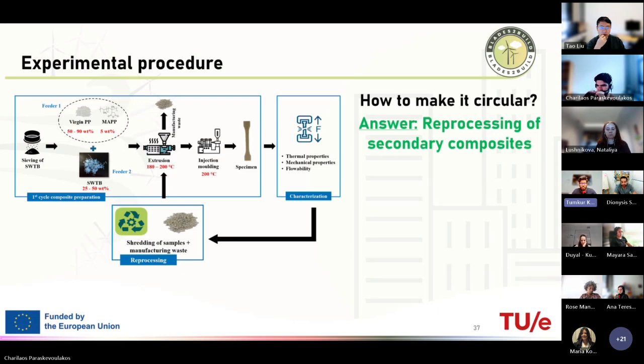So for that purpose, we also investigated how reprocessing of these secondary composites will work on the new polypropylene composites. For that, we shredded the specimens which were produced from these materials and then re-extruded the material, and also did the injection molding. So this cycle went up to around 3 cycles. Now you must be wondering why we need to do the reprocessing of such composites when we actually get materials for cheaper prices.